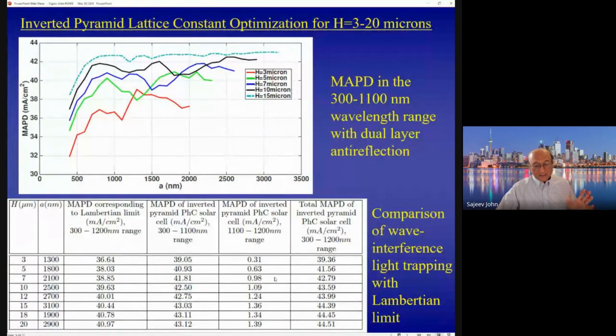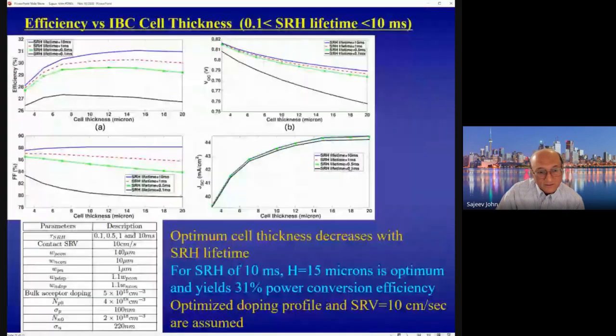So with this light trapping mechanism, we are exceeding the Lambertian limit by between 3 and 4 milliamps, which is a very substantial increase in the solar absorption and in a very thin structure. So here you see the actual calculated efficiencies that we have obtained by solving both the drift diffusion equations and the Maxwell's equations, efficiency as a function of cell thickness.